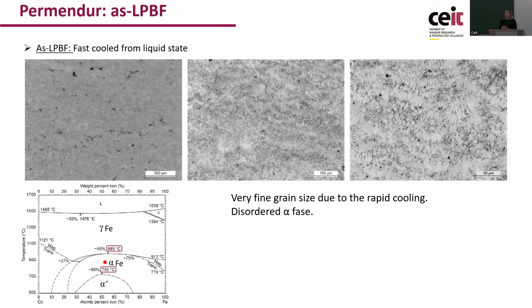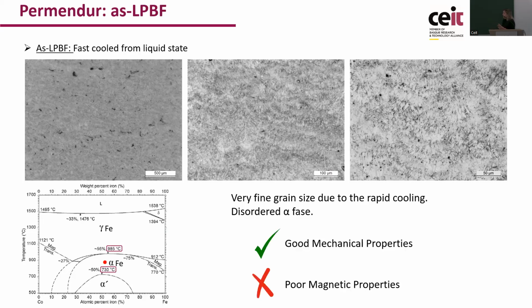So starting from the base material, that was the as-AM or as laser powder bed fusion material, this material has very fine grains because this is related with the very fast cooling rate during the process. What we observe in the X-ray diffraction experiment that I will show later is that this phase was reached in a disorder alpha phase, the one that is here in this region. So this phase has good mechanical properties, but the problem is that it has very poor magnetic properties. And as this material is supposed to be used for magnetic applications, we needed to change it.